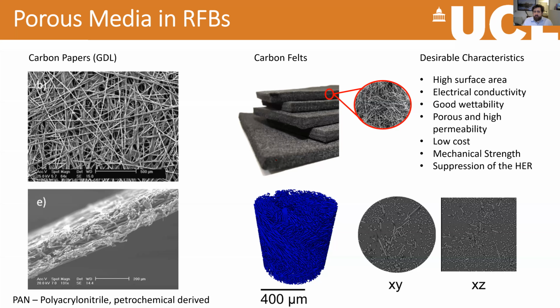And as I say, for the vanadium redox flow battery, they should actually suppress this hydrogen evolution reaction. So that means actually sometimes you're a bit limited in terms of catalysts or metals that you can use in these electrodes, because they might more favorably produce hydrogen instead of do the charging and discharging.